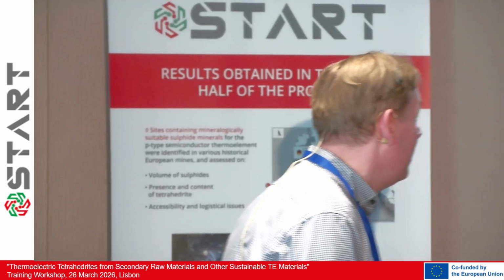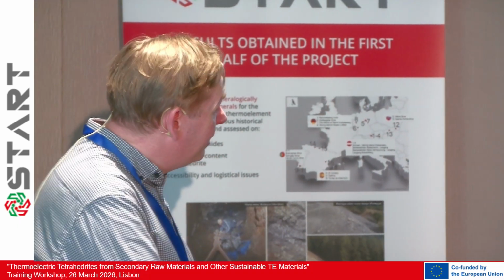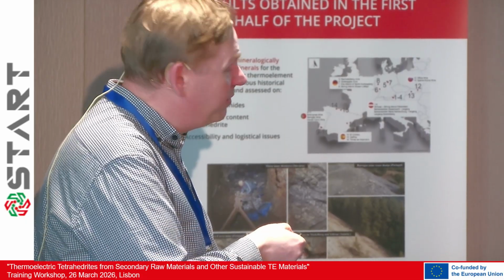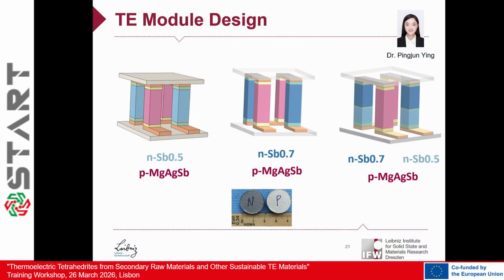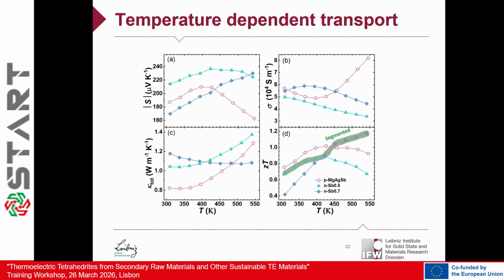One strategy to boost especially the efficiency of these modules from the beginning was to work on the N-type side with a segmentation. So we have two compositions. One has a rather small concentration of antimony, which is applied at lower temperatures, and the higher concentration of antimony is used at higher temperatures. This gives you some boost in terms of the efficiency.